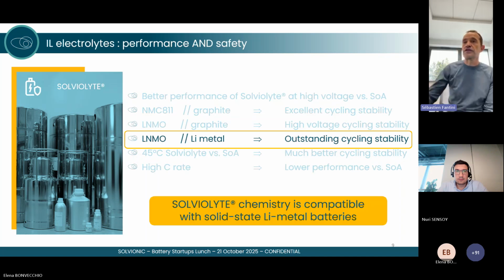So this electrolyte doesn't work only with lithium metal. Just to tell you, we also have experimental evidence, which can be shown outside of this presentation, on NMC 811 graphite, for which we achieve very good cycling stability. High voltage cycling stability also with LNMO graphite. The example that we have just seen was on lithium metal LNMO.